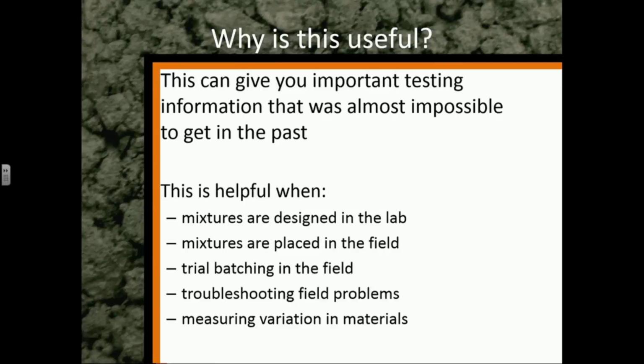They got it, and within 2 days, they found that the sand gradation had changed just a little bit, had gotten coarser, and that they were using a new mid-range admixture that they didn't realize. And when they switched back to the old one, they didn't have any problems anymore. Okay? And when the contractor saw that, they wanted a super air meter, their friends wanted a super air meter, the admixture people wanted a super air meter. There are huge benefits. People are excited when they can see the ability of how this can help them make better, more consistent concrete.